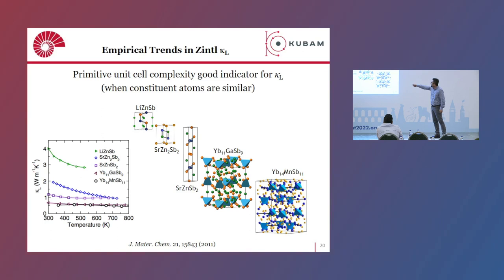You can see that this is only 6 atoms per unit cell, and as you increase the unit cell size, you introduce different local environments. Here you can reach 208 atoms per unit cell. A large unit cell and very different local environments lead to lower thermal conductivity, experimentally shown. This one is lithium zinc antimonide, and this is for the ytterbium manganese antimonide. So this is extremely low lattice thermal conductivity, and you don't need to do anything. This family of materials has a complex unit cell which inherently shows low thermal conductivity.